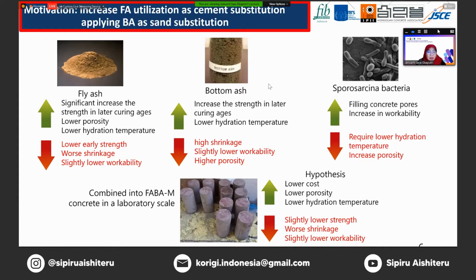We also use bottom ash as a sand replacement up to 25% to get its property on internal curing in the concrete. But of course, it has negative effect to the concrete, very similar to fly ash. And we know that it is a porous material, so it must affect the higher shrinkage in the concrete. Then we have to find the solutions. We have to find the antidote for the coal ash effect. So we use microbes in the mixture. In most of our experiments, we use Sporosarcina pasteurii as the bacteria, especially for concrete.